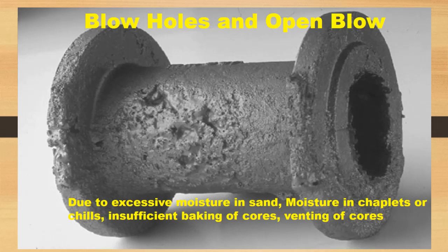Blow holes and open blows. Open blows appear as smooth walled round voids open to the casting surface, and blow holes are entrapped bubbles of gas with smooth walls. The reason for the appearance of these blow holes or open blows is excessive moisture in sand, moisture in chaplets or chills, insufficient baking of cores, or poor venting of the cores.